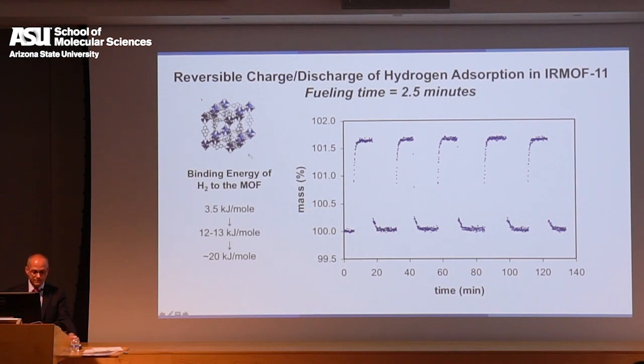And so this is the result of that experiment, where this is now at room temperature. We're taking up hydrogen over 1.5% by weight. Not a lot, but significant. And it's reversible because it's not tied to the framework by covalent bonds. So let me just make a long story short here, because this is ongoing research. We are right now with hydrogen, in terms of binding energy, the strength of interaction between hydrogen and the framework, at about 12 to 13 kilojoules per mole. And that gets you around 2% by weight. Okay, not in this structure, but in another structure that has an exposed metal site. So 2 to 2.5, if you really use the right metal, but 2.5 is the absolute maximum of where we are right now at this binding energy.